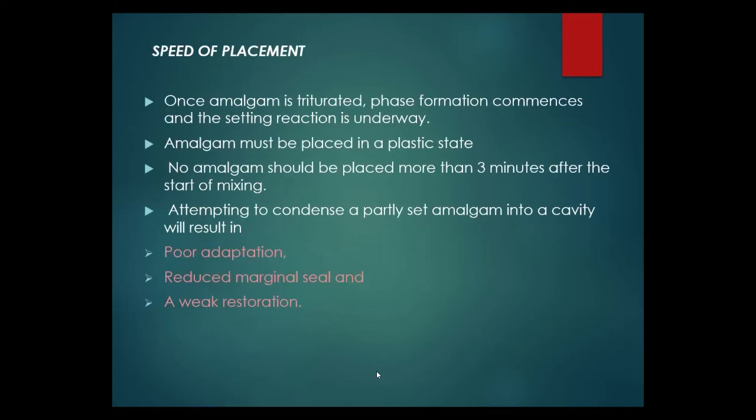Speed of placement of increments of amalgam: once amalgam is triturated, phase formation commences and the setting reaction is underway. Amalgam must be placed in a plastic state. No amalgam should be placed more than 3 minutes after the start of mixing. Attempting to condense a partially set amalgam will result in poor adaptation, reduced marginal seal, and a weak restoration.